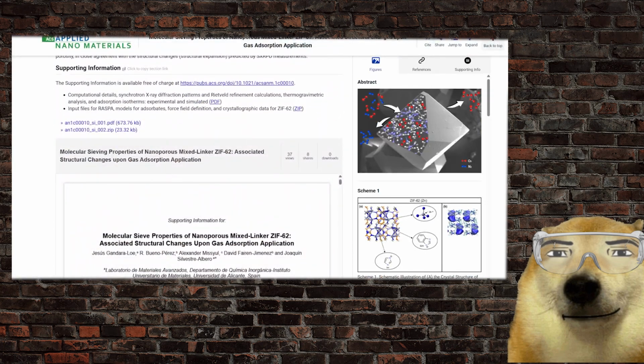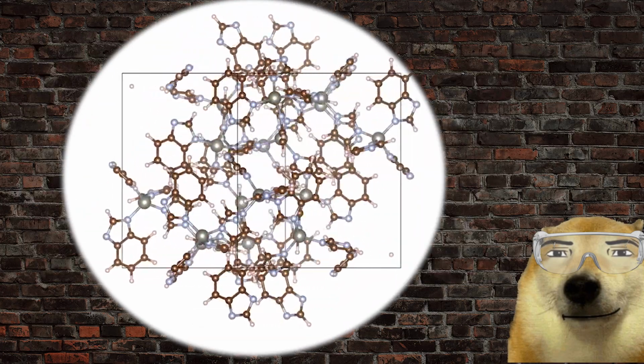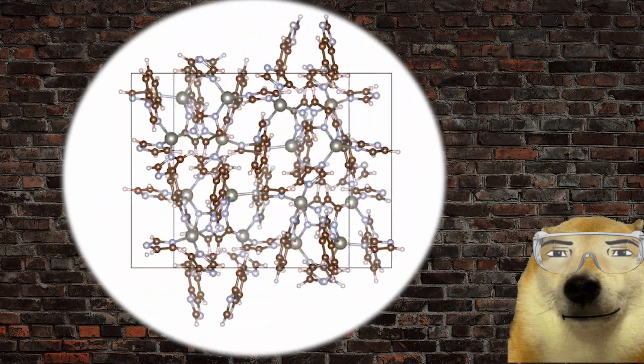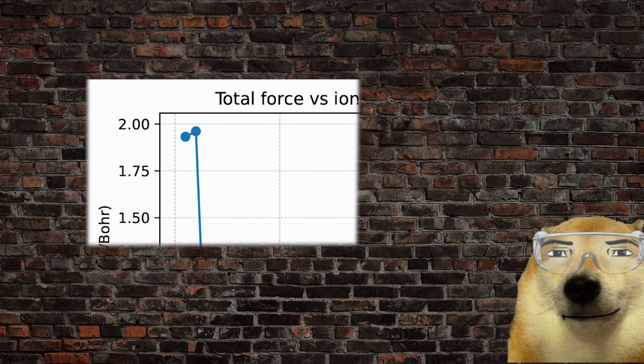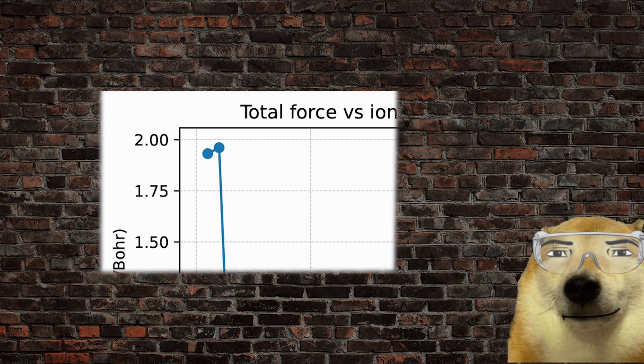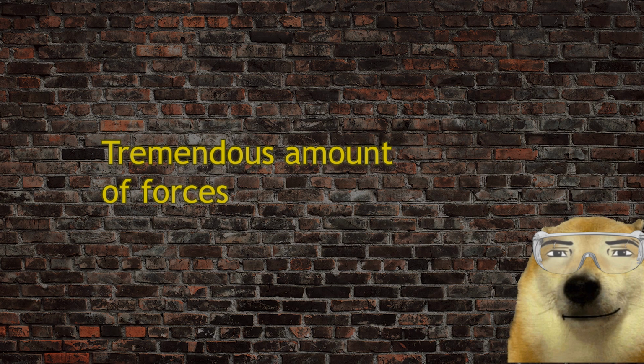The file, however, was still not perfect for our use as it wasn't geometrically optimized. To optimize such a structure means to minimize the forces present in the system. The structure had almost 2 hartree per bohr of force present, which is roughly 10,000 times more than what would be sensible for us to use in our later melt-quench simulations, so we had to change that.